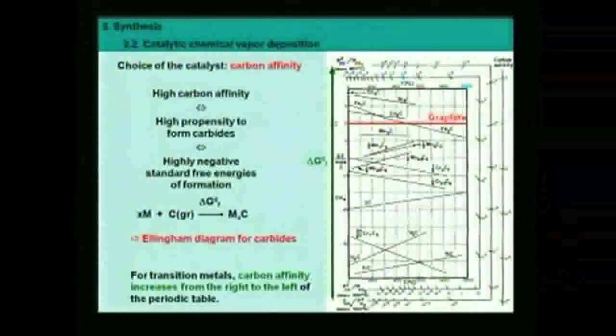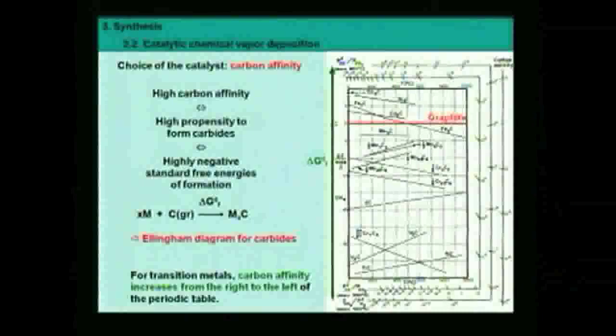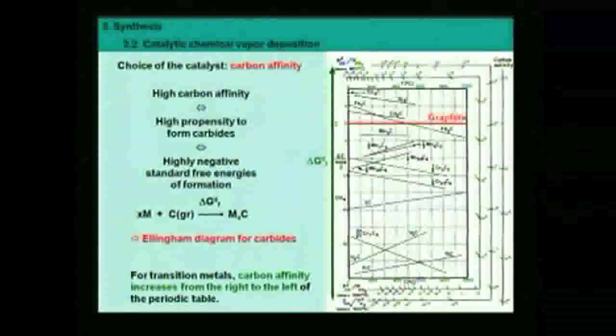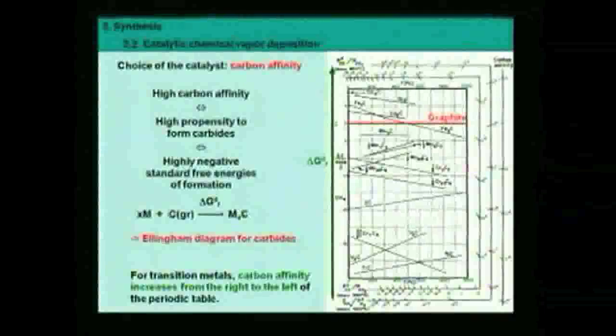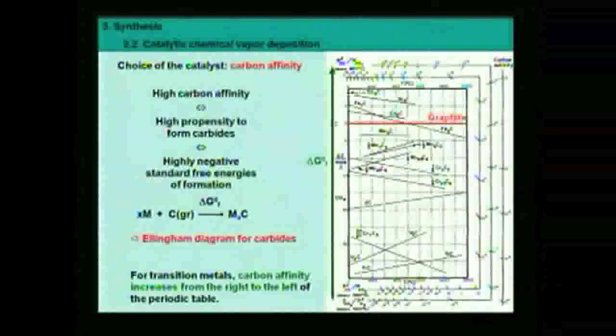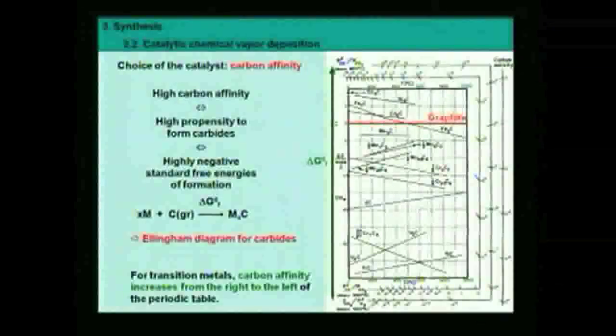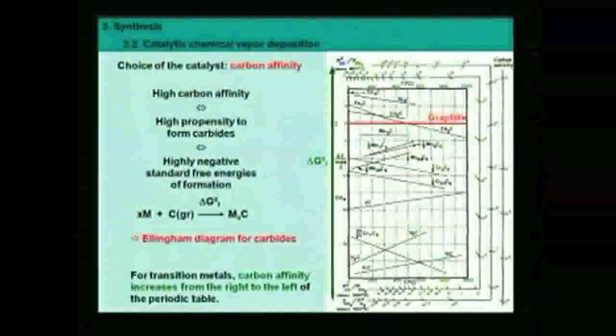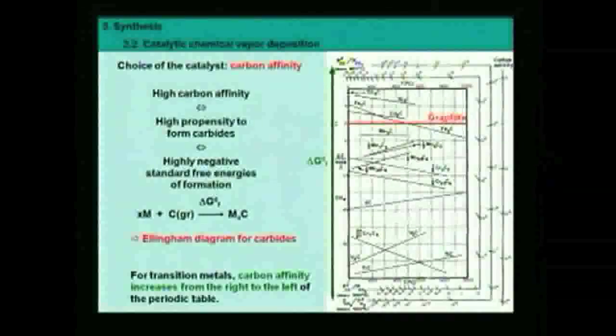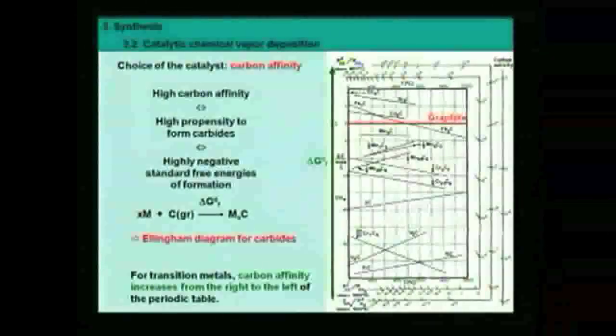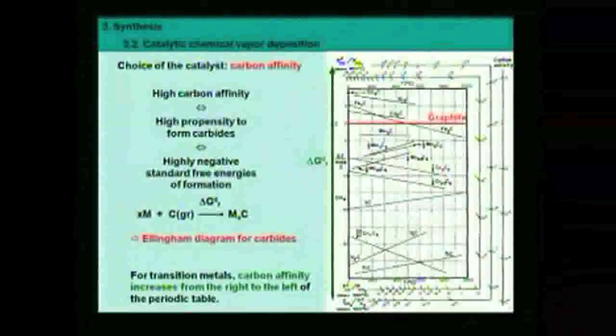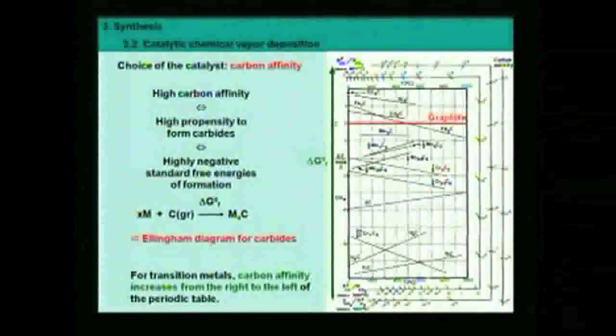So those carbides are sometimes observed, but not for a long time. Usually, they readily decompose into graphite and metal. Okay, this is just the inverse reaction. Not in this direction, but the other way. Okay? Because we have a positive free energy of formation. So this gives you another idea of the carbon affinity of the different elements. Those elements at the left of the periodic table like to bind to carbon, and those elements do not like too much to bind to carbon, but a little.